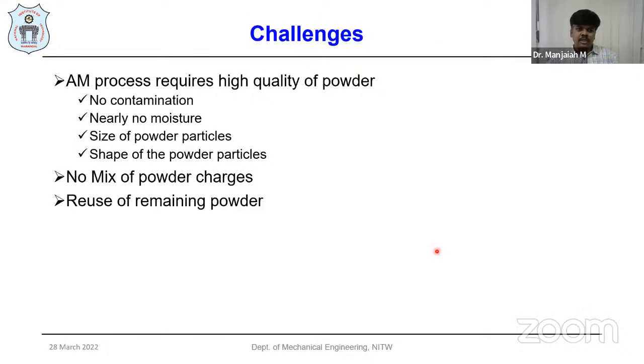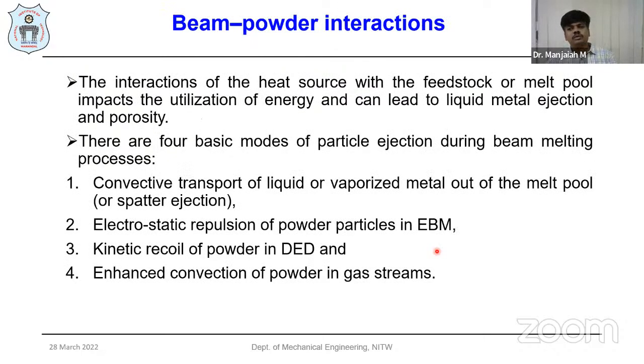The other challenges: the AM process requires high quality powder, with no contamination and nearly no moisture. As for the particle size, we have to use 5 to 45 microns for SLM, that is powder bed fusion, and 45 to 90 or 110 microns for DED systems. The shape of the powder particles should be very spherical, because flowability is very important. Sphericity and powder size distribution give us the flowability and compressibility ratio in the powder bed fusion process, which gives very good quality of each layer. And there should be no mixing of powder charges, and the reuse of remaining powders should follow a standard. We have to use one third reused powder with the virgin powder when using reused powder.